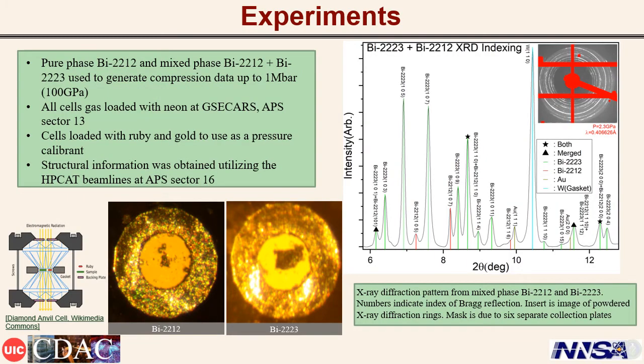Samples of pure phase BSCCO 2212, 2-layer, and BSCCO 2223, 3-layer, were loaded in diamond anvil cells, and the chambers were cryogenically filled with neon gas at APS Sector 13. Ruby and gold were used as pressure standard.